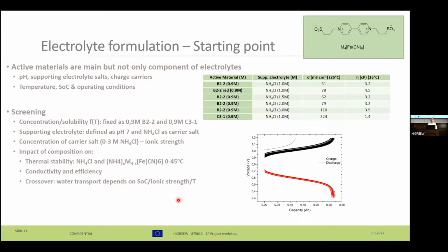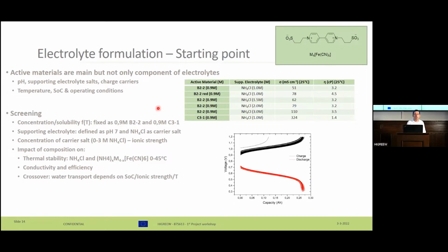So at this point that we have already defined the active material, we turn into the part of the electrolyte formulation. So this is kind of a new beginning, a new starting point. Why? Because the active material is an important compound here in the electrolyte, but as well we have to consider other aspects such as the pH, supporting electrolyte salts, charge carriers, and the effect of temperature, SOC, and operating conditions on those. So we can see clearly here in this graph in which we are depicting different compositions of the electrolyte by means of increasing the concentration of ammonium chloride going from 1 molar to 3 molar.